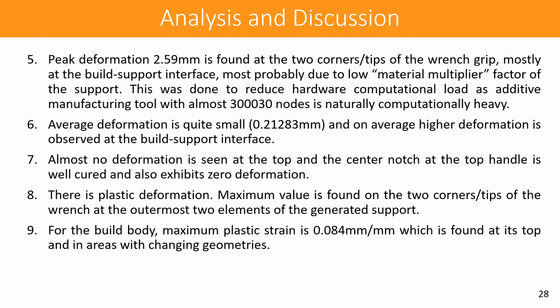Peak deformation of 2.59 mm is found at the two corners or tips of the wrench grip, mostly at the build support interface, most probably due to a low material multiplier factor of the support. It was kept low in order to reduce hardware computational load, as an additive manufacturing tool with almost 300,000 nodes is naturally computationally heavy.